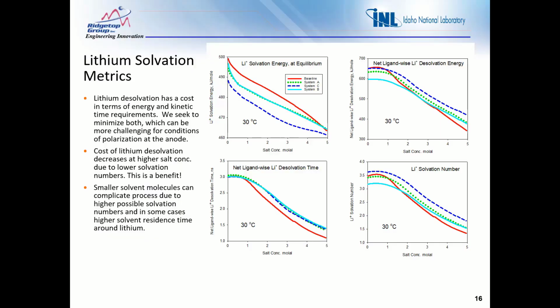As we go down to the plots below, we also have the net ligand lithium desolvation time. Again, this is kind of mirroring what we're seeing above with the ligand-wise desolvation energy. And then we have the total lithium solvation number in the lower right panel, which is kind of a starting point. Again, this is another indicator of relative strength of solvation between a given set of solvents and lithium, and how it might be screened and optimized for particular applications.